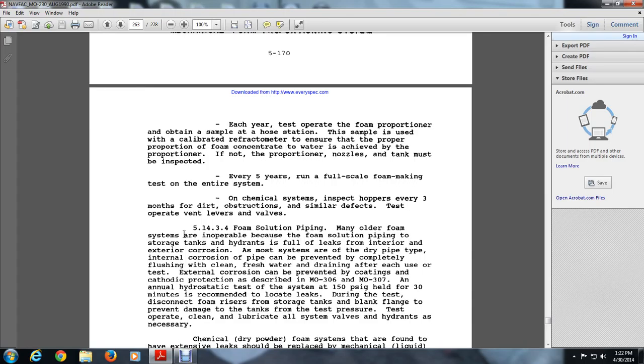5-14-34, foam solution piping. The main cause of the system being inoperable is the foam solution piping, the storage piping, the hydrants, from leaks of the interior, or exterior corrosion. Most systems are of the dry pipe type. Interior corrosion of the pipe can be prevented by completely flushing it clean with fresh water and draining after use. External corrosion is prevented by coatings and cathodic protection as described in MO 306 and MO 307. Annual hydrostatic test of the system at 150 PSIG and holding for